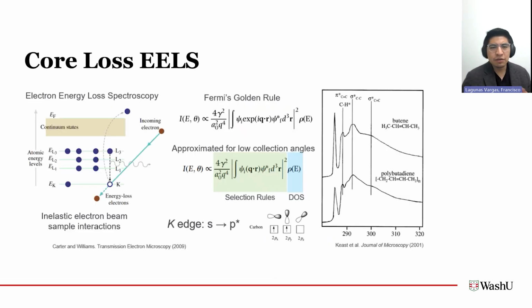And to try to figure out what the issue was, we turned to core loss EELS. So in core loss EELS, you can not only see whether or not you have your carbon or titanium or oxygen present, but based on the fine structure of your carbon K edge, you can actually see different transitions that are induced by the electron beam and correlate those to the bonding of your material. In polymers, this is really well understood, and we should expect to see different types of bonding based on the amount of carbon double bonds, carbon-hydrogen bonds, carbon-carbon bonds, and so on.